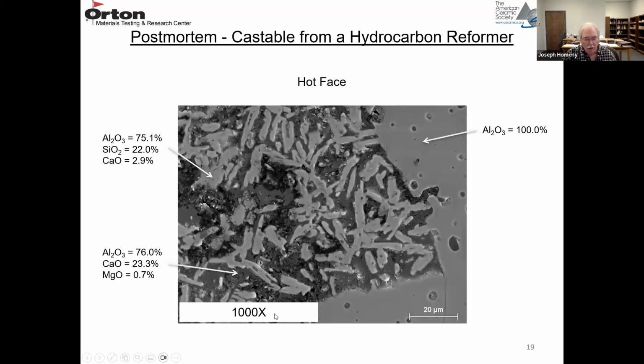So a higher magnification right at the hot face. You can see an alumina crystal right here. There's another one right here. This porosity pattern to me indicates it was a tabular alumina product. That's the residual porosity. So this is a high purity dense tabular alumina. So that's the aggregate. And then this is the matrix.